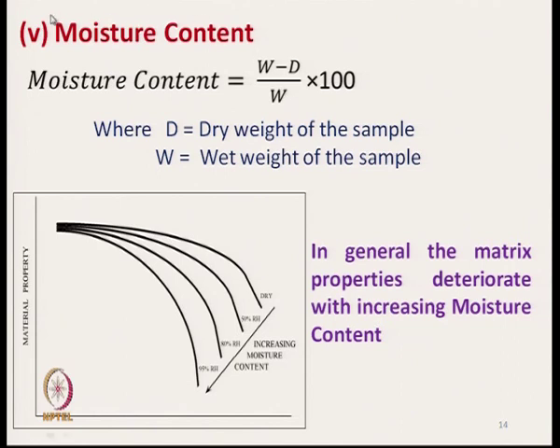Moisture content is measured by measuring the dry weight of the sample and the wet weight of the sample. First we take the normal weight, that is the wet weight of the sample, then we dry the material to remove the excess water inside it, and the difference, that is (W minus D) by W, when expressed in percent, is called moisture content.